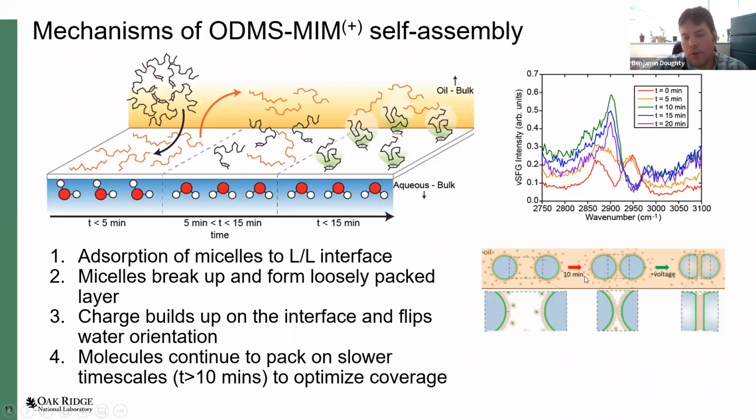Well, what ends up happening is you form the monolayer very quickly, but you form a monolayer that's so dense that it has a hard time interdigitating with each other. So these tails don't want to intermingle with each other to form a bilayer because these things are packed in so tightly. So salts are good in forming an interfacial monolayer, but they're not necessarily very good in forming a device using one of these DIBs.